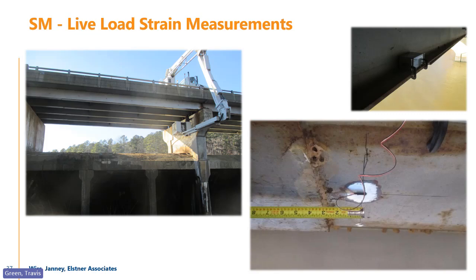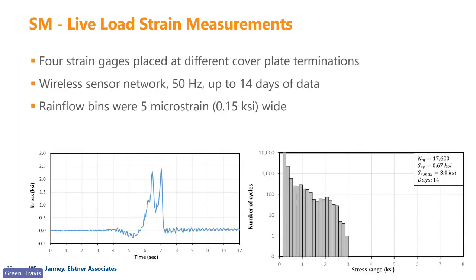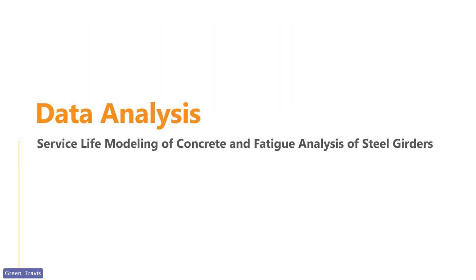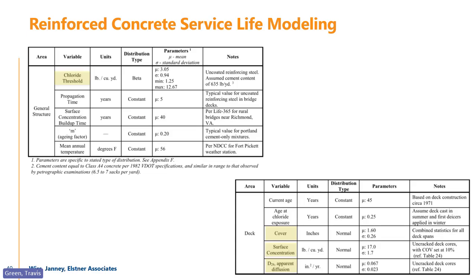Right. So the next step is, on this particular bridge, we did strain gauges with a wireless data acquisition system to look at strains at the ends of the cover plates on the bottom right. This is the cover plate, so we're looking at cover plate termination stresses, right? And this is one of the cellular nodes that we used on this particular project. We got strain data. We did rainflow analysis, which is kind of separate from the service life modeling, but it's really talking about what our fatigue life is, right? And then we analyze data, so we're analyzing both the concrete data and the steel data for this particular project, right?